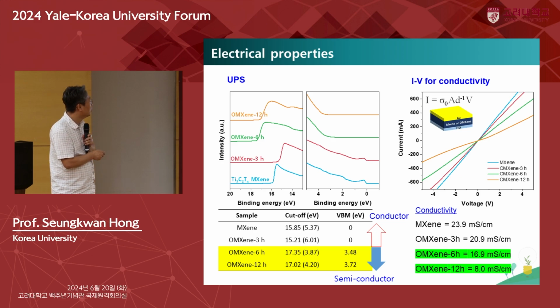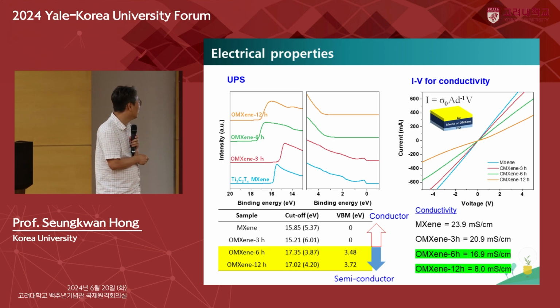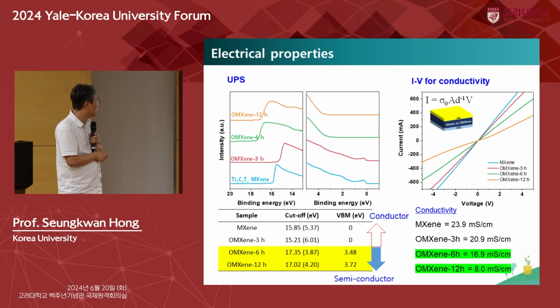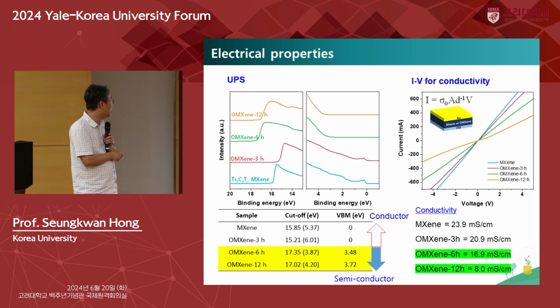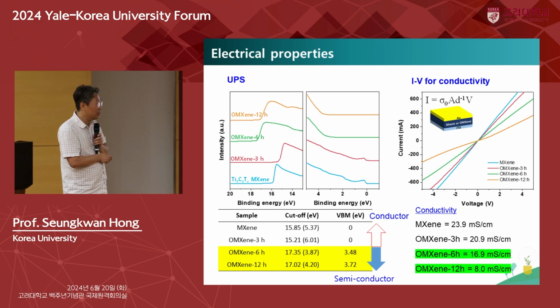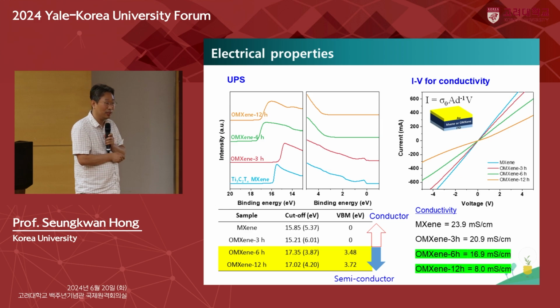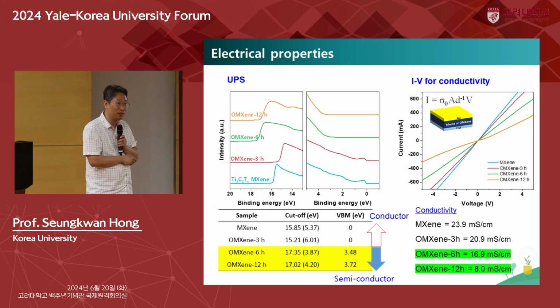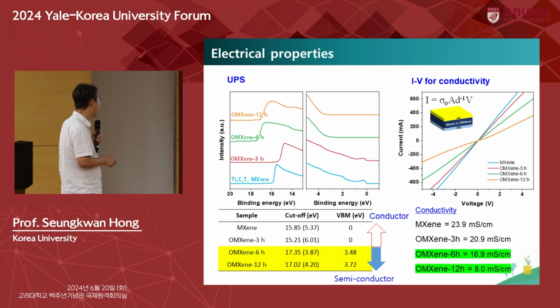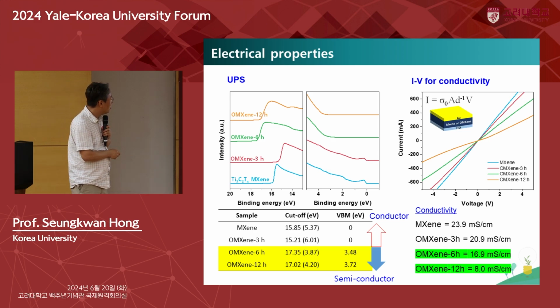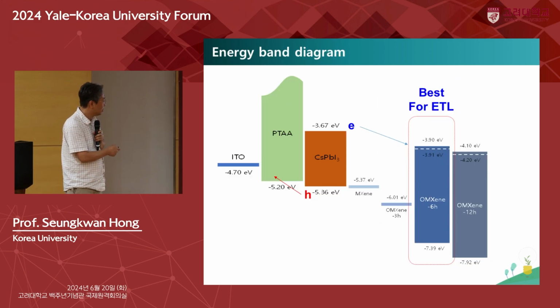So with this UPS and this IV for conductivity, we can characterize their properties. Basically, like graphene, the MXene is a conducting material. So with less than 3 hours oxidation, the MXene has conductor properties. So the conductivity is high. But over 6 hours oxidation, the MXene changes to a semiconducting material. So it has a valence band, and so from here we chose the 6 hour oxidation MXene. So this is the band gap. So the 6 hour oxidation is the best to use for that concept.